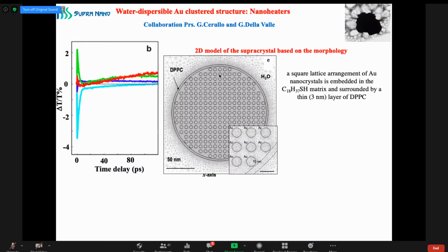After internalization, you keep the self-assembly, but the size is more or less a factor of 10 larger compared to the dispersed particle in water. You can see that the particles self-assemble in specific regions, and we keep more or less the shape, but what is important, we keep the self-assembly. And for the supraball, we also keep the self-assembly.